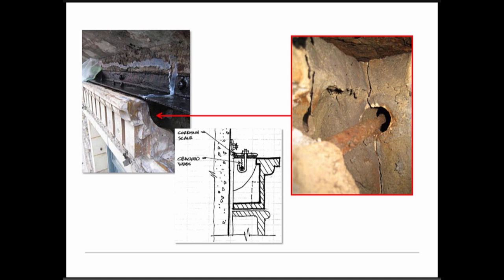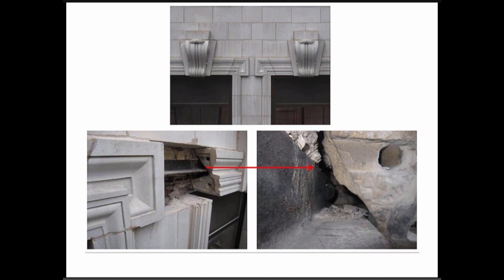Hung lintel units with an angle above, J-bolts, and a horizontal rod can experience corrosion on the underside of the angle pushing down on the lintel, causing the web within units to crack — which is invisible from the outside. This means the support holding the unit is being lost and the unit can fall. Contractors sometimes modify units during installation, notching the webs around the angle so the unit isn't properly bearing or supported.